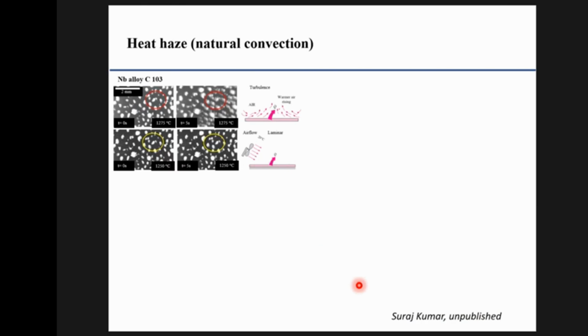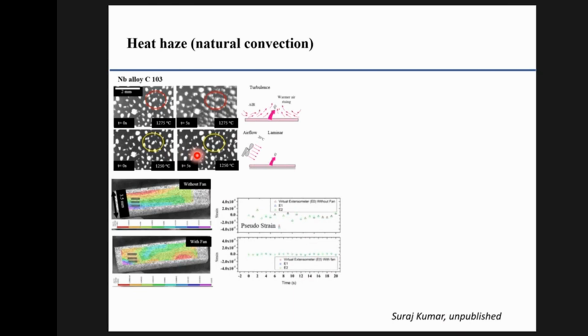Heat haze. The natural convection from a hot surface will cause refractive index changes, and this is a bit uncontrolled. So if you have this haze where you have all this hot air rising from the surface, your sample rapidly blurs. Whereas if you use a light fan, just to maintain some laminar flow conditions past the surface, then you'll see that everything remains nice and highly resolved. These are strain measurements with no stress, so essentially it's measuring the background noise in your system. You'll find that with the heat haze, you have all these fluctuations, but with the laminar flow, you have a nice horizontal line, which is practically zero. So you have to do this if you want the highest strain resolutions.